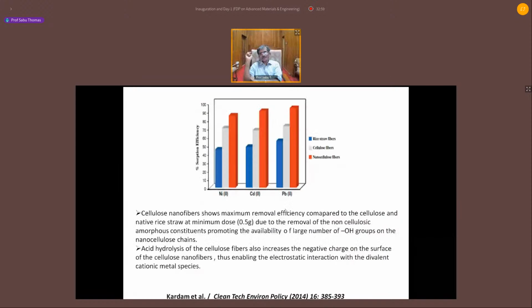Nickel could be removed, nickel 2, cadmium 2, lead 2, all these will be removed. This is basically because acid hydrolysis of cellulose nanofiber provides negative charge, so nickel and cadmium, which have positive charge, can have electrostatic interaction. So if you look at this rice straw, cellulose fiber, nanocellulose, see, nanocellulose is much more efficient.